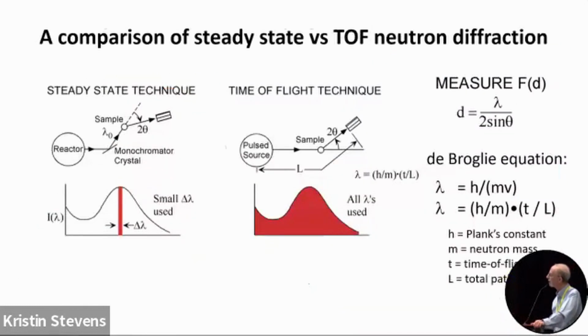So this is a comparison of steady state versus time of flight diffraction. Typically with a steady state reactor, one would select one wavelength of neutrons with a monochromator crystal. And then there's a sample, and the detector would step through some 2 theta angles to collect data. And so in the Bragg equation, we're varying sine theta and lambda is a constant.